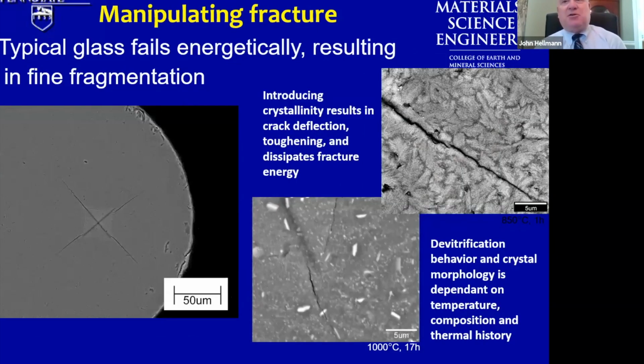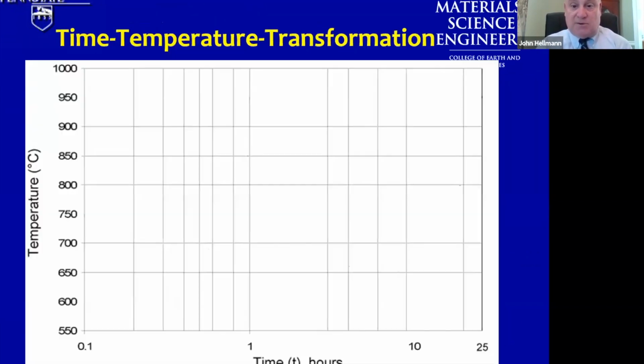But that was enough to do PhD theses. And what we hypothesized was that if we could take that vitreous material and subsequently devitrify it to the crystalline phases that it wishes to be in, that we could alter the fracture mechanisms in such a way to achieve a higher toughness while retaining some strength, and that these beads would fail in that type 1 failure mode that's desirable for propping. So we did that.